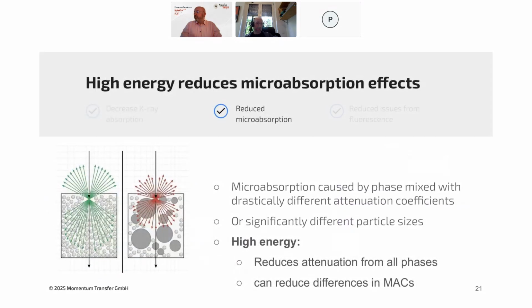We also get reduced microabsorption, and this is particularly important for phase quantification. So if you have a mixture of different minerals in your sample, different minerals will have different mass attenuation coefficients. And that basically depends on the mass of the unit cell and the volume of the unit cell and the weight percent of that material in your sample. And it's also affected by particle sizes. So if you have very big particle sizes, it gets even worse. That part's a bit hard to predict. But generally, you ideally want particles or crystallite sizes in the range of about 1 to 5 microns.